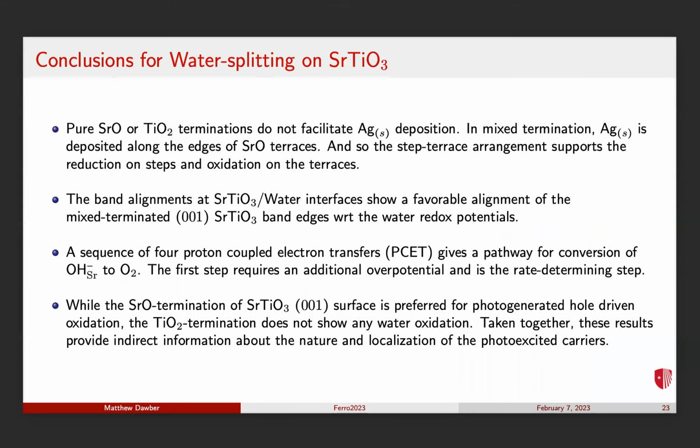So these are the conclusions then, right? You can't really do this with either pure SRO or pure titanium dioxide. That's certainly what our experiment showed. And it showed also that you needed to have these 2 terminations in close proximity to each other for the reaction to occur. So then we look at the band alignments. The band alignments look okay, right?